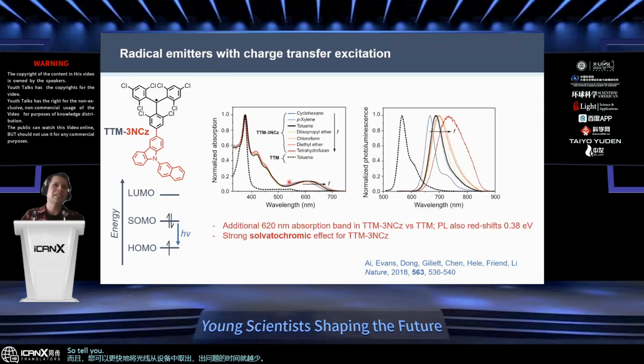To tell you a little bit about this material and how to think about it, so this radical, when it's combined with hole transporting materials, acts a bit like an electron acceptor. So when you photoexcite this material and you put it into more polar solvents, it actually undergoes a strong solvatochromic shift as it redshifts the emission, something that you expect in a charge transfer type or electron donor acceptor type dye.